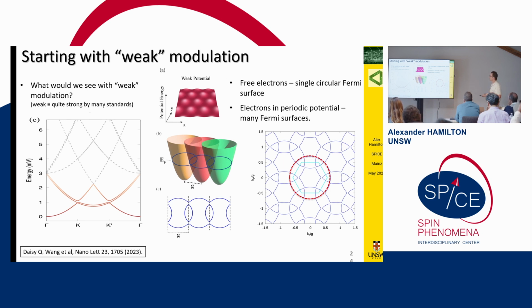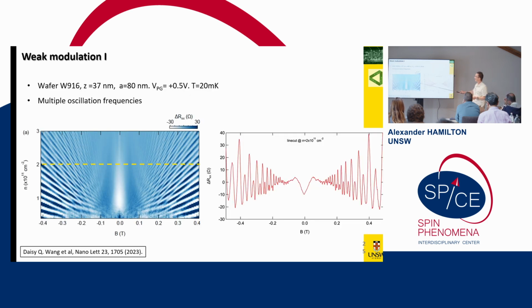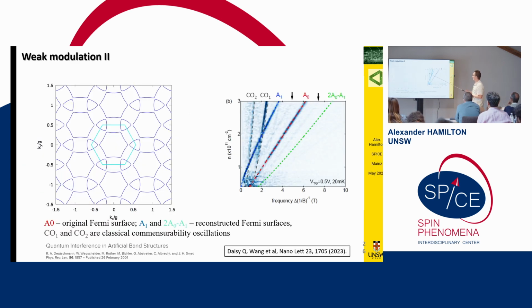And so what you might expect to see is some signatures in the magnetotransport of these additional replica Fermi surfaces. This is the magnetoresistance as a function of magnetic field. You see Shubnikov-de Haas oscillations, but superimposed on those is an additional frequency. You can do this for a whole bunch of different electron densities, and you can see beating patterns in there due to the multiple frequencies. And whenever you see multiple frequencies, the first thing you do as an experimentalist is take a Fourier transform. So this is the Fourier transform as a function of electron density.